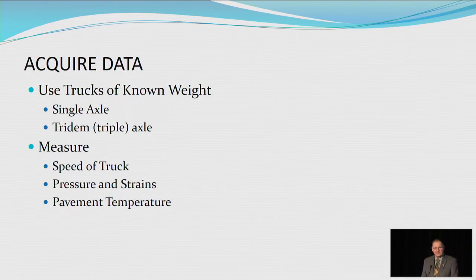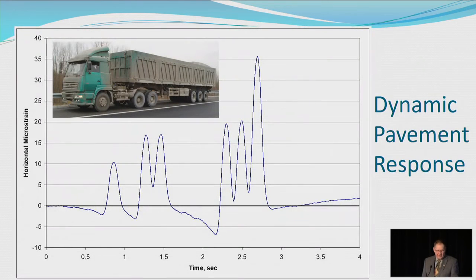Now, what we wanted to do with these sections is to acquire some data. So essentially the experimental process was to calibrate those pavement sections so that they almost became like strain gauges. In other words, we were planning to run trucks of known weight across the pavement where the gauges were in each of those 5 sections, do that at different times of the year when the temperatures are different, and you can get a curve of strain versus temperature for any given load. So here you can see one of the trucks that we were using.